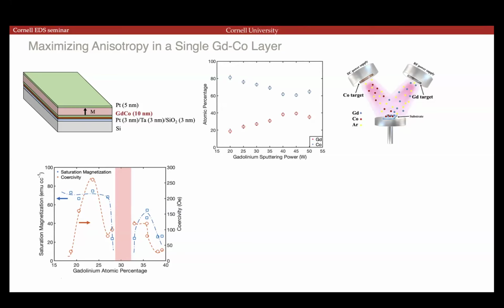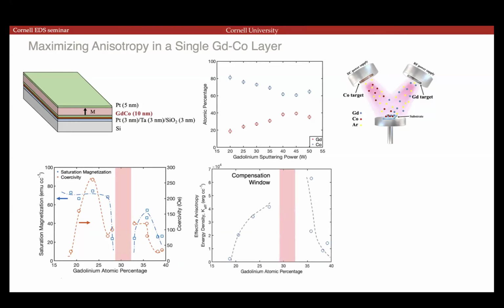That same composition, just to either the left or the right of it, is where the anisotropy suddenly shoots up. So we wanted to operate just either to the left or to the right. We chose to operate at gadolinium 35, cobalt 65, sorry. And then we measured the anisotropy to compare the two and determine which one has the highest anisotropy and therefore the highest bandwidth. And you can see that the gadolinium 35 cobalt 65 has the highest anisotropy.